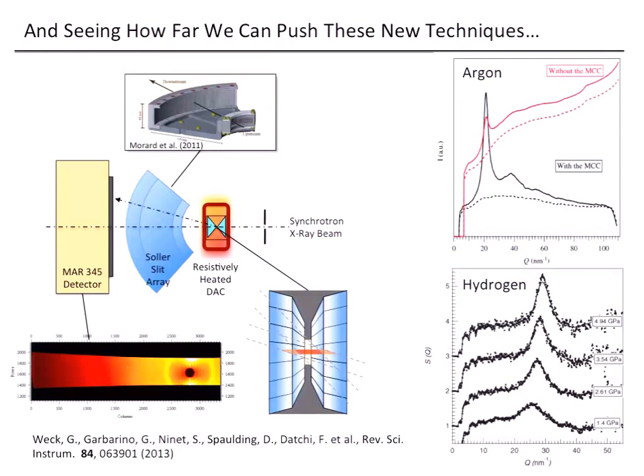So this is another thing we spent a lot of time doing, implementing this Soller Slit Array to reduce the background. The problem with trying to do diffraction on these very low Z materials is that you have a huge Compton background from the diamond anvils themselves, because they're usually many, many tens of times thicker than your sample. Your sample may be on the order of 10 microns thick in between the diamonds, but you've got up to a millimeter of diamond on either side.